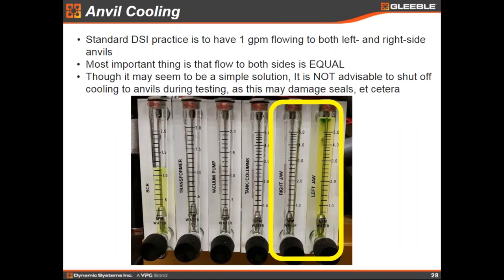Another consideration is anvil cooling. We typically recommend one gallon per minute flow to both left and right side anvils or jaws for practically all testing — that's a baseline. More important is that they're equal: you want both sides to cool equally, or you're probably not going to have the thermal gradient you want across the sample. It may seem like a good solution to shut off the cooling since we're working to improve thermal gradient, but that is not advisable. If you allow the whole jaw or anvil base to heat up to testing temperatures, you may cause damage to your seals or hardware. It's never advisable to shut off cooling entirely.